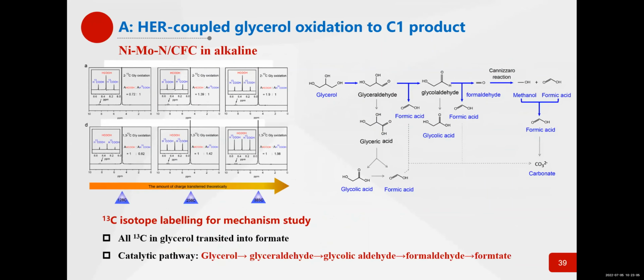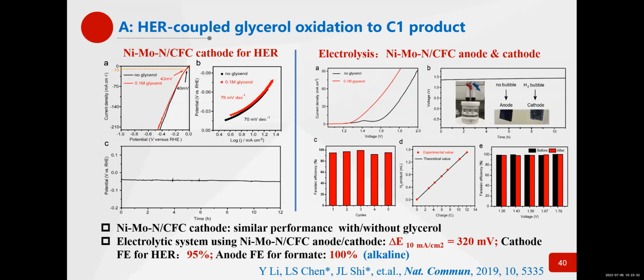And then we have probed the whole reaction pathways, by using carbon-13 isotope labeling technique. And this is the whole electrocatalytic pathway of the oxidation of glycerol to finally formate. I will not go into much detail of this process. And then we also use this kind of catalyst as the cathode for HER. That means these materials can be used as the catalyst at both anode and cathode. At the anode, it also shows relatively high activities for the OER. And then we establish a two-electrode system for the electrolysis of water and glycerol. And use this